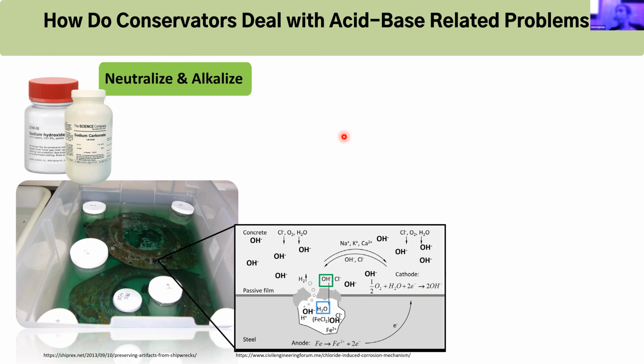these hydroxy ions, when there's enough of them, become the most common portion of the solution at this point, and our iron will then preferentially start forming salts called iron hydroxides. Iron hydroxides are much more stable than any type of iron chloride product. And this actually becomes almost its own built-in buffer, because all of a sudden you have this built-in source of hydroxy ions in this corrosion product.